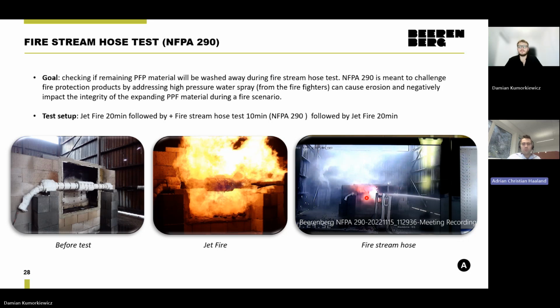New member of our test reports, the stream hose tests. This is quite a new standard for us, I would say, even though it's been a couple of years ago now. It's an American type, I would say, test designed to simulate the effect of an impinging fireman hose on the specimen. So in the case of fire, there might be cases where water cannons or active fire measures may be taken. And the purpose of the test is actually to see that the impingement of the fire hose water jet does not compromise the system mid-fire scenario. So in the test, we're doing 20 minutes of jet fire, 10 minutes of water hose spray, and then another 20 minutes of jet fire. And the system has to withstand the water spray without cracking due to the thermal shock or that type of thing.